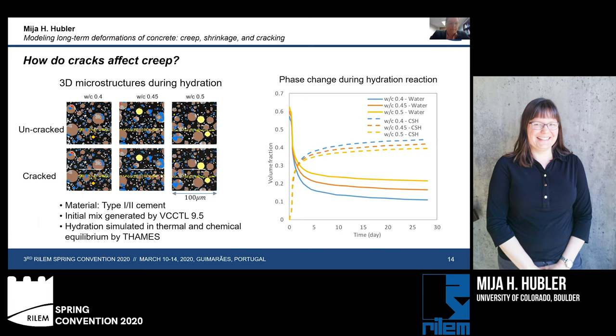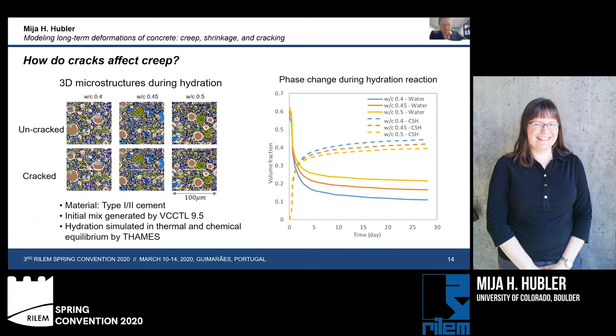Now let's turn our attention to creep. What are the cracks doing to the creep? We can simulate the hydration of the cement. I initially tried to study this experimentally and found that the cracks that are starting and impacting the creep are so small that it's hard to study this experimentally.